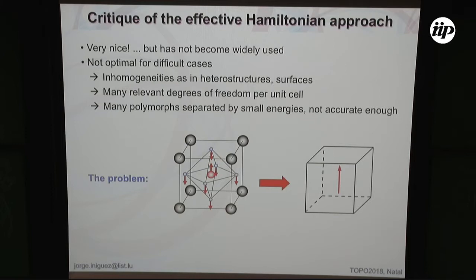There are a bunch of situations that are more and more scientifically relevant but become more and more intractable with this original approach. Plus, this original approach, as successful as it is for ferroelectrics, hasn't been used anywhere else in materials science — which is a strike against it. The problem essentially is a very drastic approximation: you forget about the atoms and work with effective variables corresponding to specific patterns of displacements. This is probably why nobody outside ferroelectrics has worked with these models.